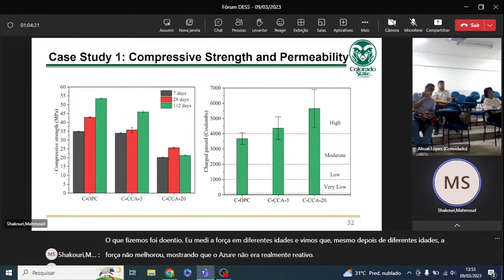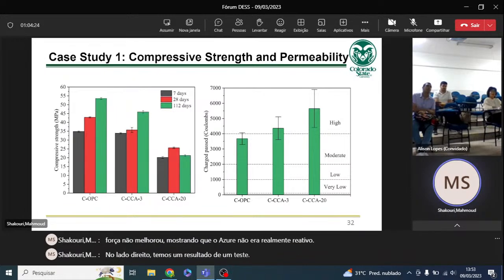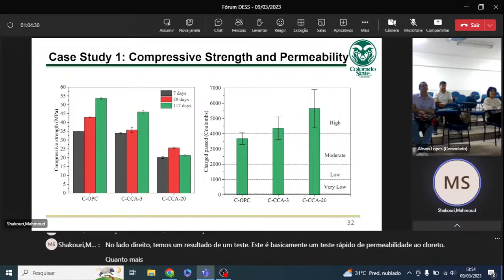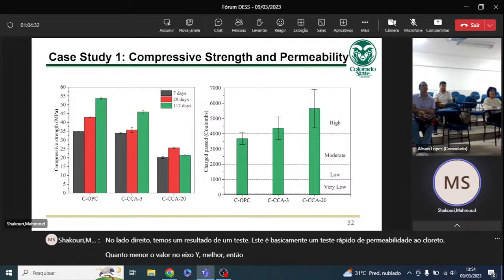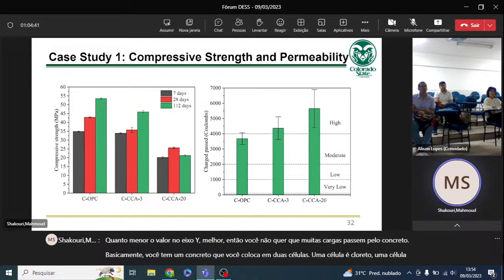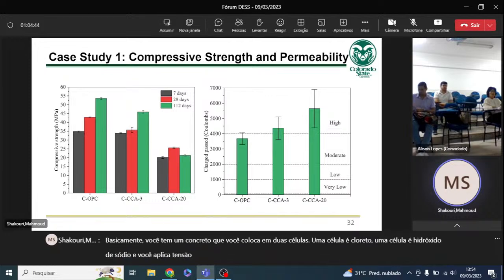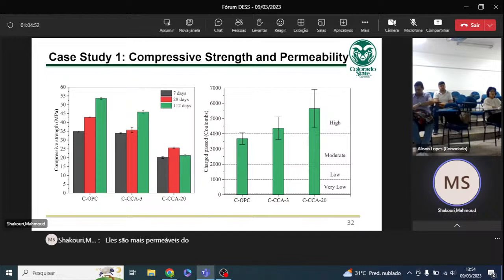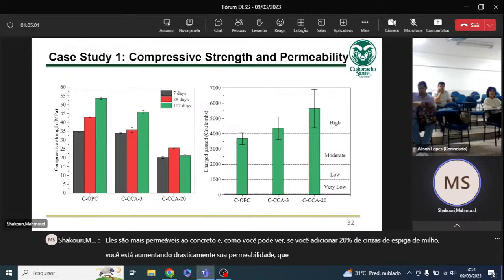On the right side, we have the result of a test. This is a rapid chloride permeability test. The lower the value on the y-axis is, the better. So you don't want too many charges to pass through your concrete. Basically, you put the concrete between two cells. One cell is chloride, one cell is sodium hydroxide, and you apply voltage, and you see how many coulombs or charges pass. The higher the passage, the more permeable your concrete. And as you can see, if you add 20% corn cob ash, you're drastically increasing your permeability, which is not a good thing.